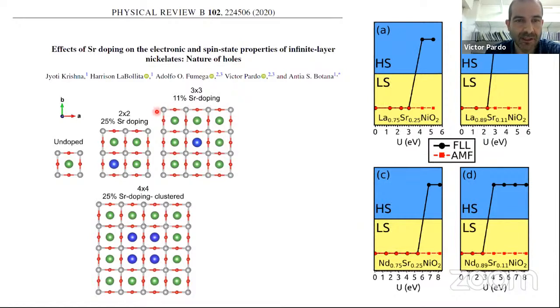the electron counting in the materials that were found to be superconductors, where you have one strontium in 9, with 8 neodymiums. And also we did this one, which probably is not the energetically favored situation, but it helps us. We basically clustered 4 strontium atoms here around a certain nickel, and this helps us understand the electronic structure of what would be nominally a nickel 2+ dopant. Here we would be able to see what the density of states is of this nickel 2+ dopant, and that will be interesting, even if in reality the dopants don't want to cluster that way.